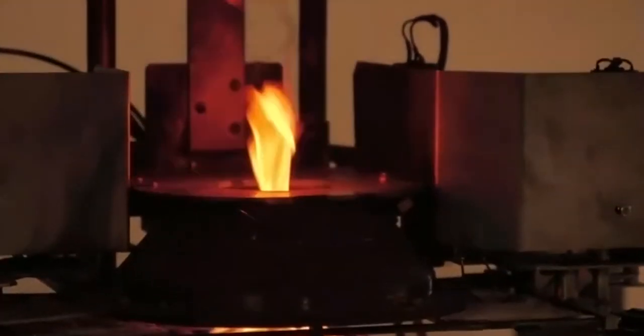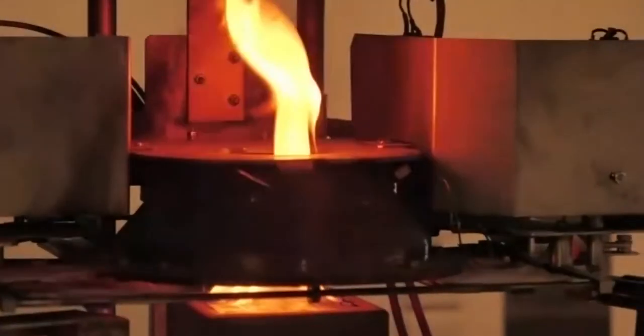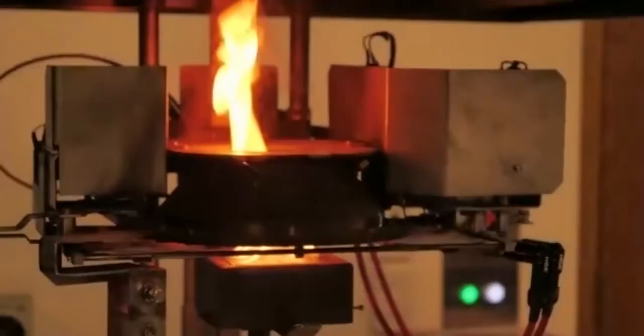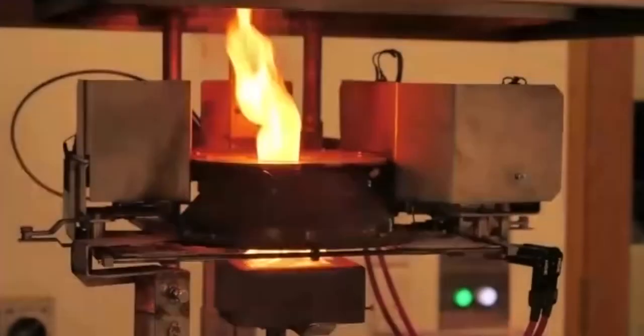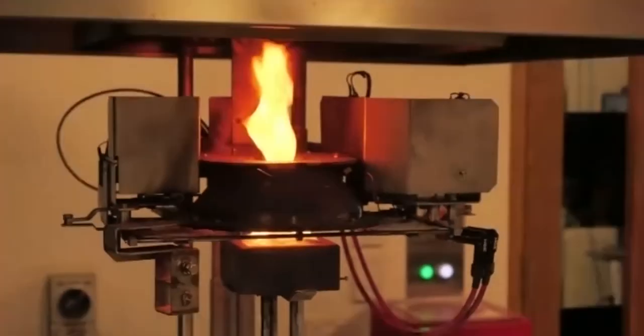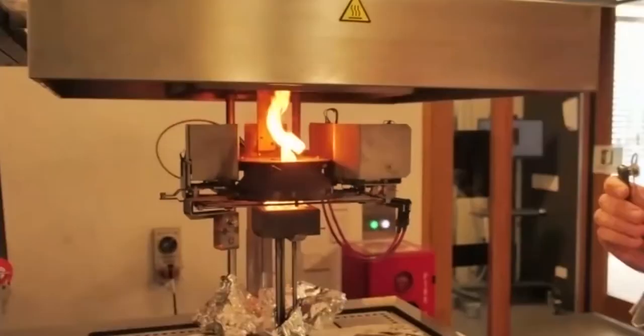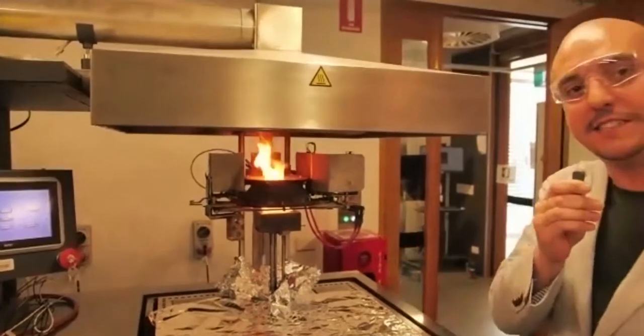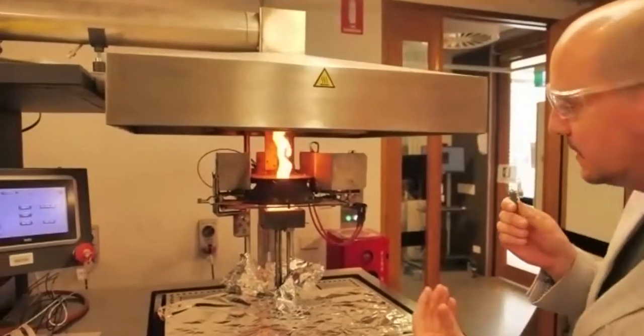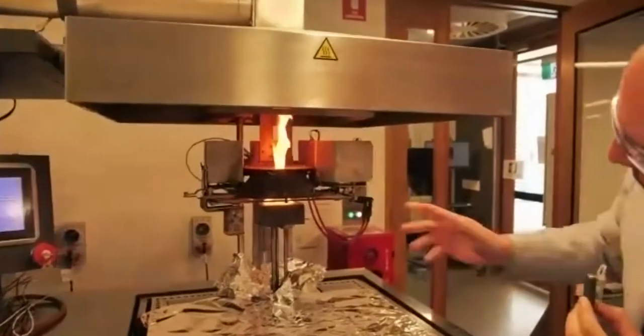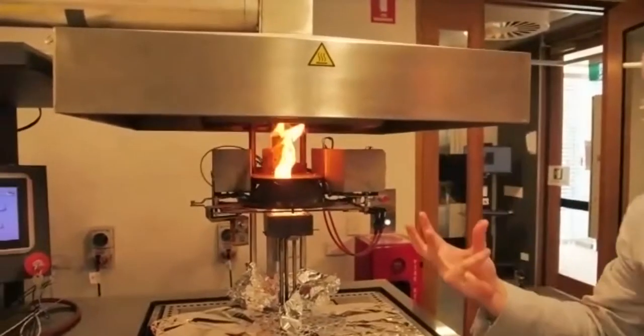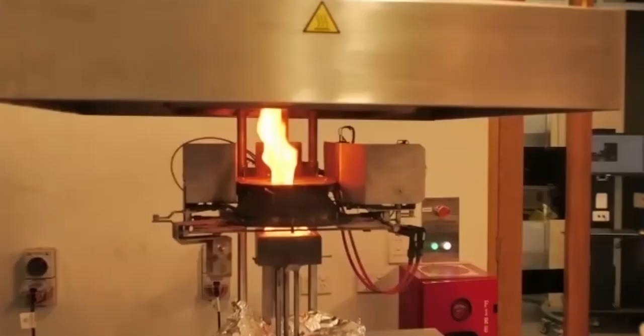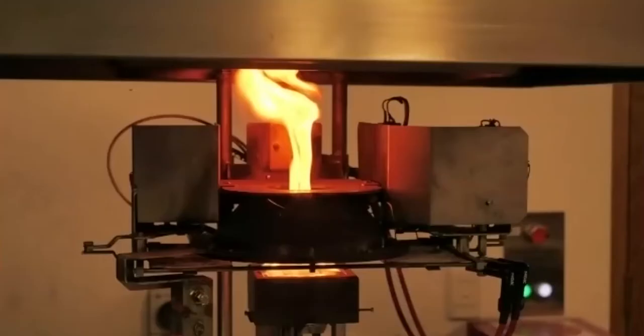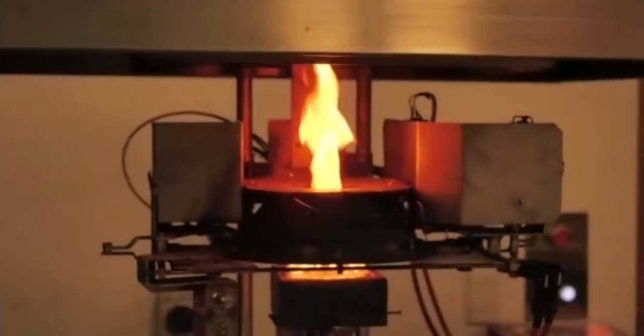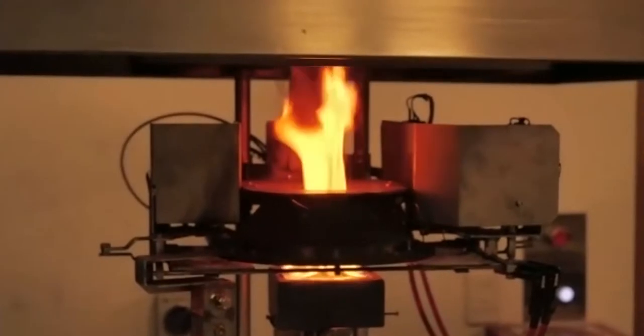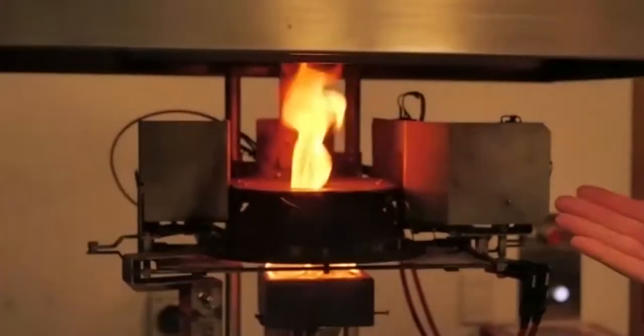Now, during this burning process, the material is going to start losing mass. So what we are going to see is that with this scale, the amount of mass starts to reduce. At the same time, you can see that the fire intensity starts to increase. How do we see that? We can see that the flame is getting bigger and bigger. That's because we are reaching a steady state of burning behavior that is controlled by the energy balance between the heater and the sample itself.